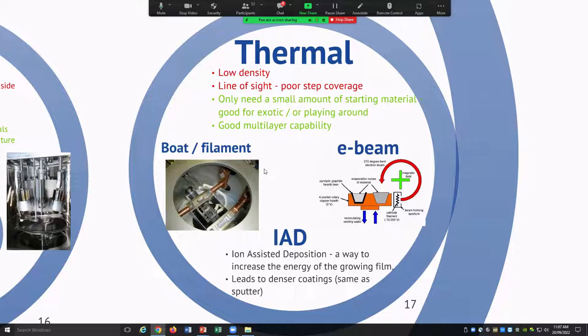How you melt the sample, you can just hook it up, put it into a thermal boat, send a lot of current through it and get it very hot that way, a resistive boat. Or you can create an electron beam and then use magnetic fields to control that electron beam and heat it up with an electron beam. To help improve the density of the coating, you can also put in an extra energy source, and that's an ion gun, and then create ion-assisted deposition. So what we've got at the university, we've got an electron beam with IAD, and it starts getting close to the similar sort of arrival energy or density of coatings that we get out of the sputter coater.